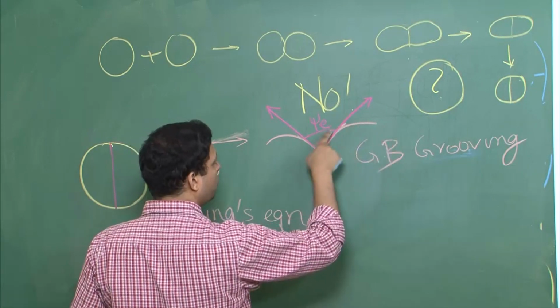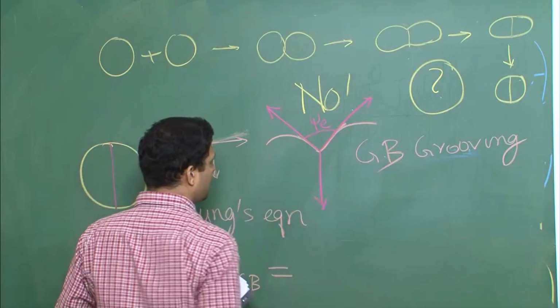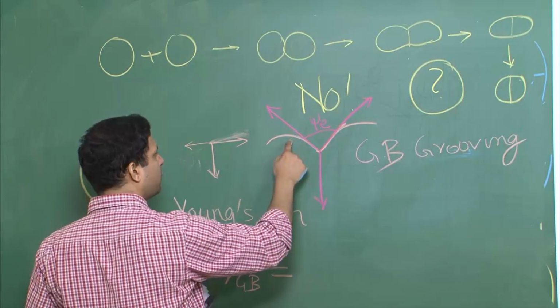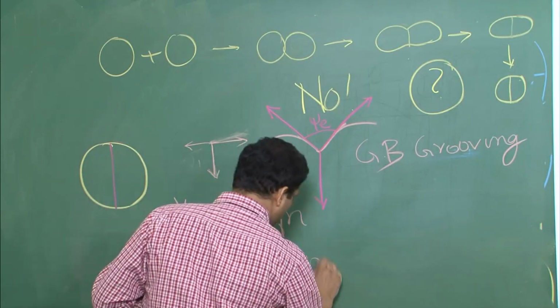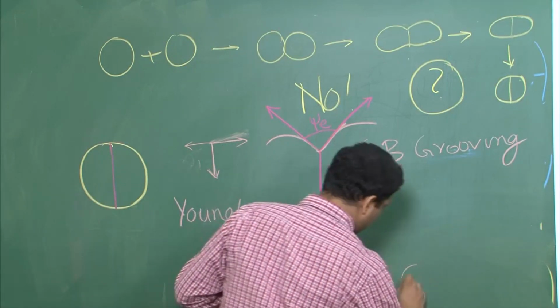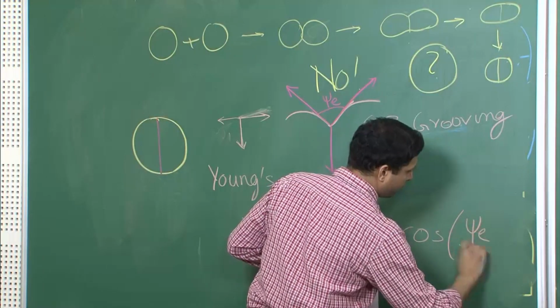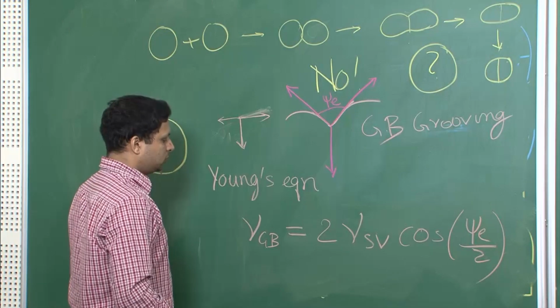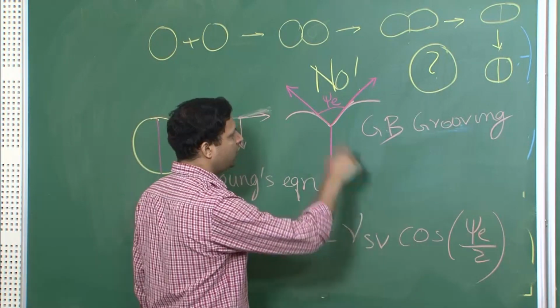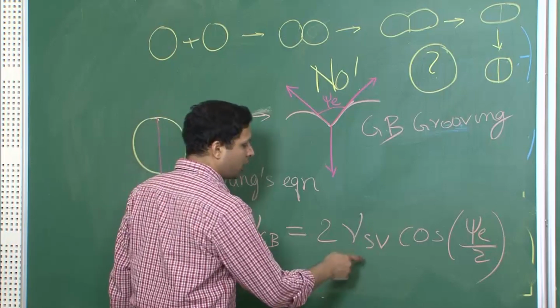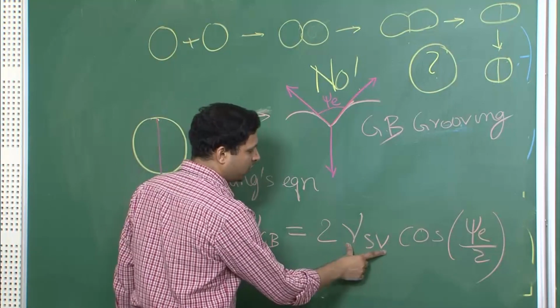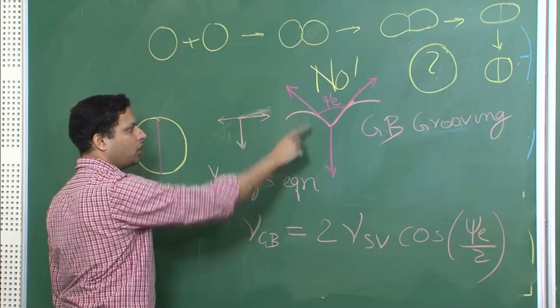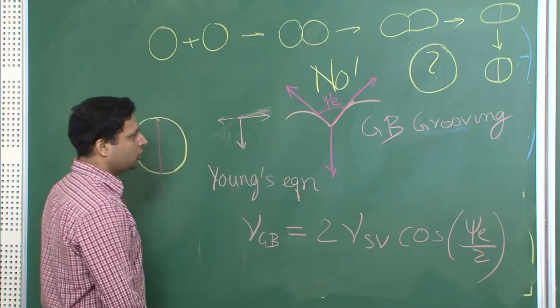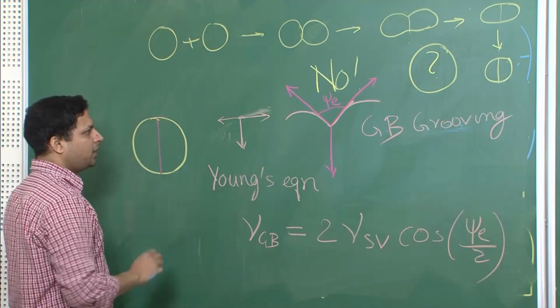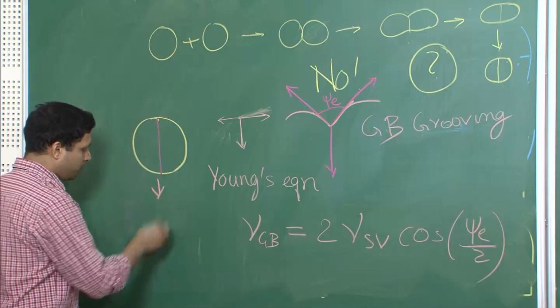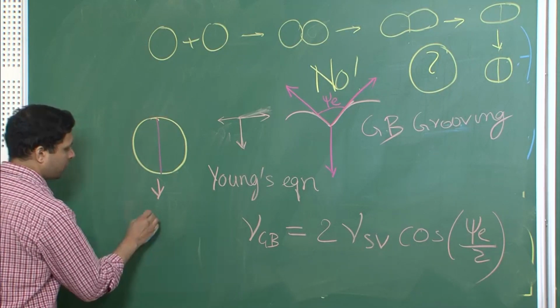you can even find out what is the grain boundary energy if you know the solid vapor energy of these two. So, this can be written as gamma SV cos psi E. So, gamma GB can be given in terms of gamma SV, and you can measure psi E experimentally. In other words, if you know grain boundary energy, you can calculate gamma SV, and if you know the psi E value, which you can measure easily. So, this is the psi E angle, and that would mean that the final shape should look like something like this.